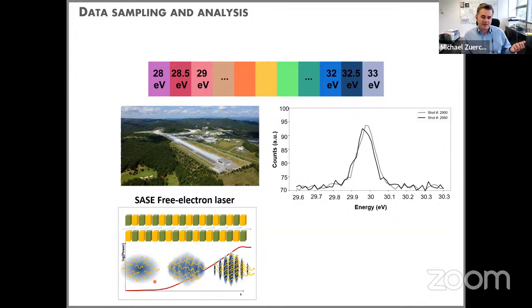So every shot in such a SASE free electron laser has a slightly different spectrum, slightly different amplitude. These lasers are not like the visible light lasers that we are usually accustomed to, where every pulse is almost identical, very constant, with very low fluctuations. Those FELs actually jitter around in photon energy and amplitude. Here I will replay it again. What you see are individual FEL shots of this free electron laser at a nominal center photon energy of around 30 electron volts. You can see it jitters in energy, it jitters in amplitude.